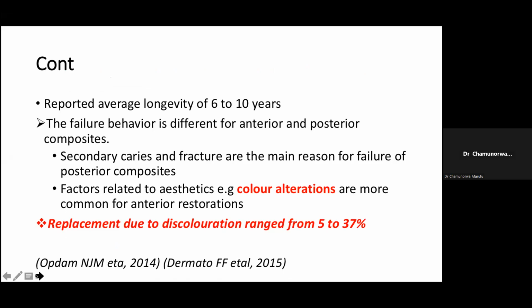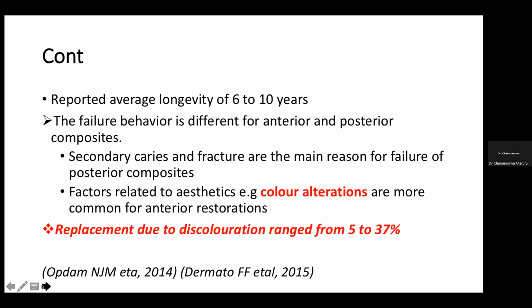All right, so dental resin composites are perhaps the most important direct restorative material in our clinic. Nowadays, we use it for both anterior as an aesthetic restoration and also the posterior restoration because of the phase down of amalgam due to mercury concerns. The longevity of this restoration, according to literature, varies significantly, but it's generally reported to be around 6 to 10 years. And the failure behavior, however, is different for anterior versus posterior composites.